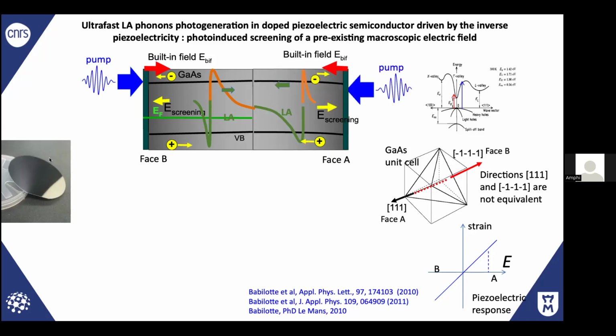If you do the same thing on the other side, in phase A, you have the same thing, but in that case the strain pulse is of opposite sign. So the consequence is what? If you look at the detection, we are in the Brillouin geometry, in the sense that we probe nearly below band gap, and we just detect a single component of the strain pulse.